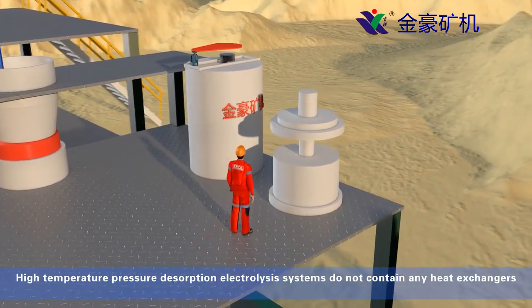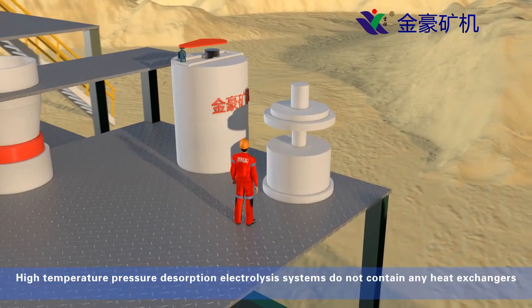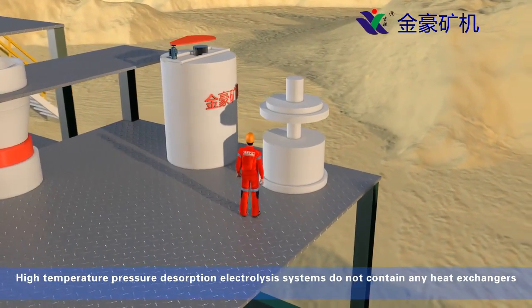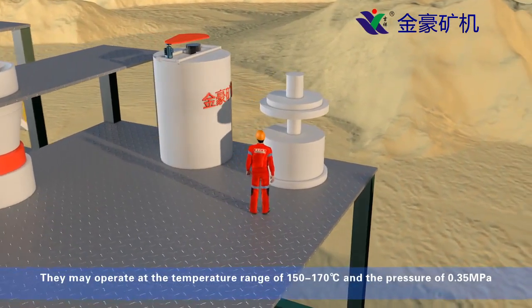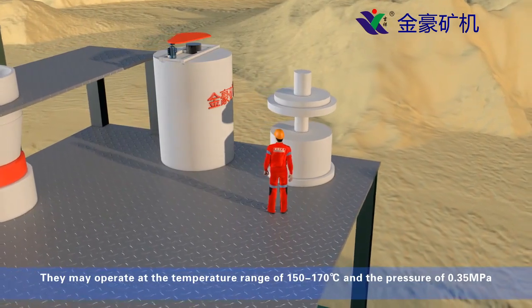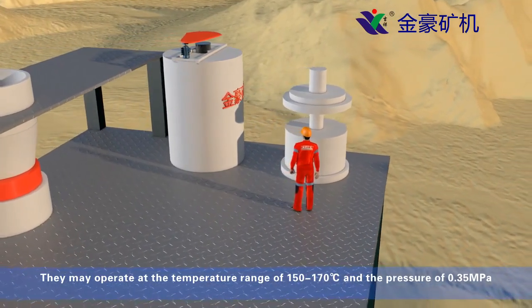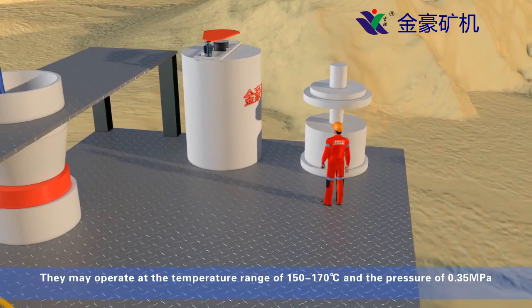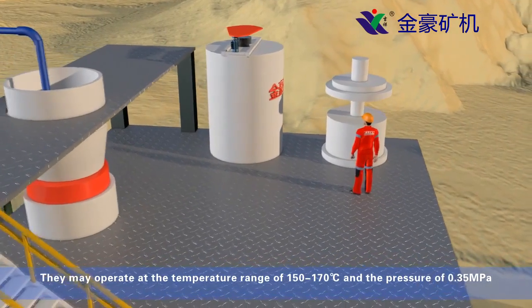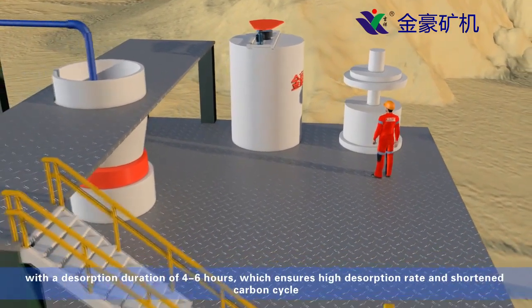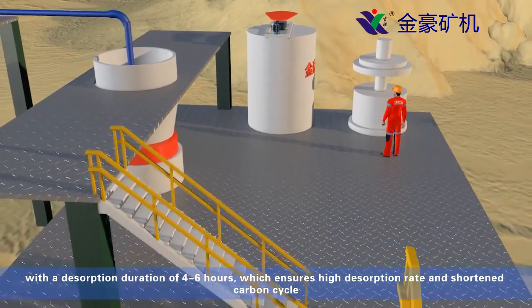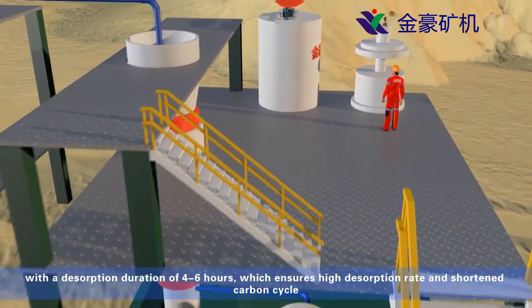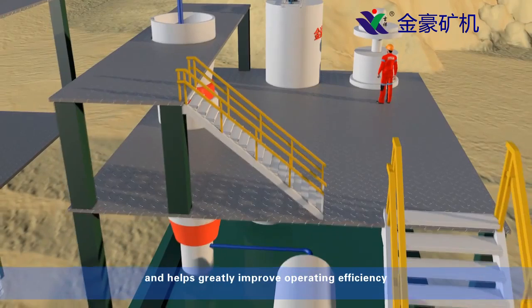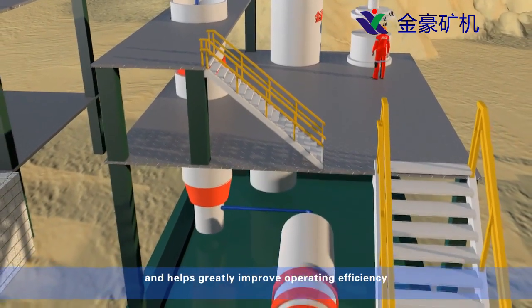High temperature pressure desorption electrolysis systems do not contain any heat exchangers. They may operate at the temperature range of 150 to 170 degrees Celsius and the pressure of 0.35 megapascals, with the desorption duration of 4 to 6 hours, which ensures high desorption rate and shortened carbon cycle, and helps greatly improve operating efficiency.